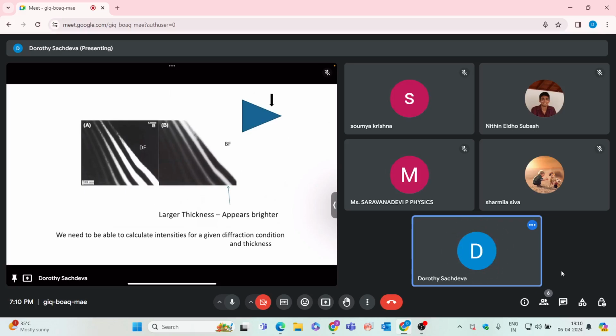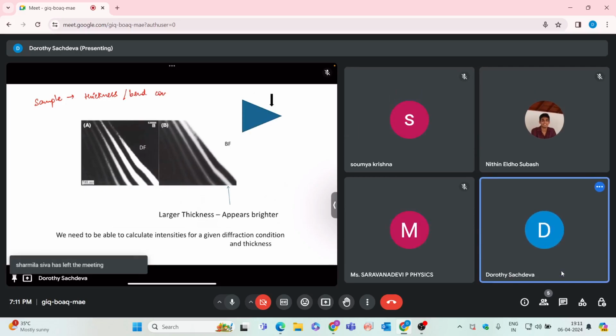So basically, the sample can have thickness or bent contours. If your sample is bent uniformly in a certain direction, or it has a thickness difference, like in this wedge-like sample, then there is this thickness difference. This is thicker and here the specimen is very thin. So then you will have these bright and dark fringes. In the bright field, these bright fringes appear due to this thickness variation in your specimen.